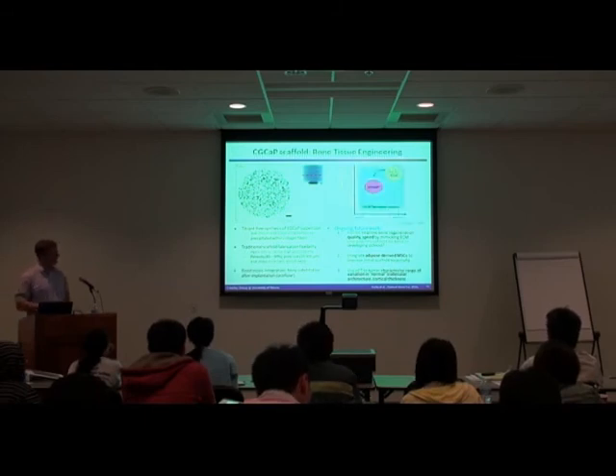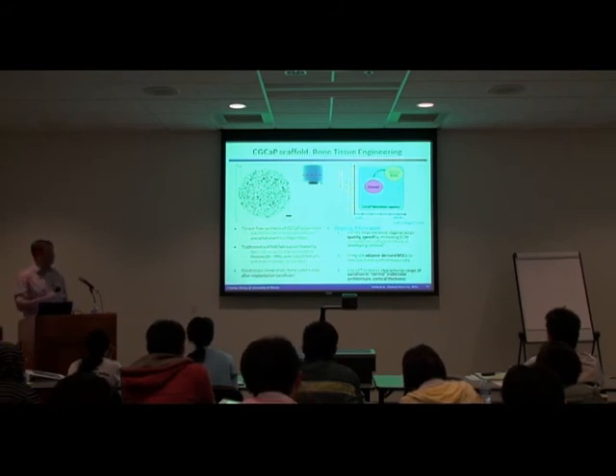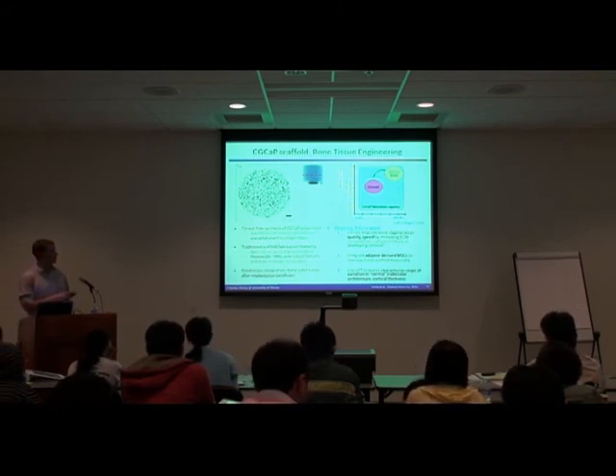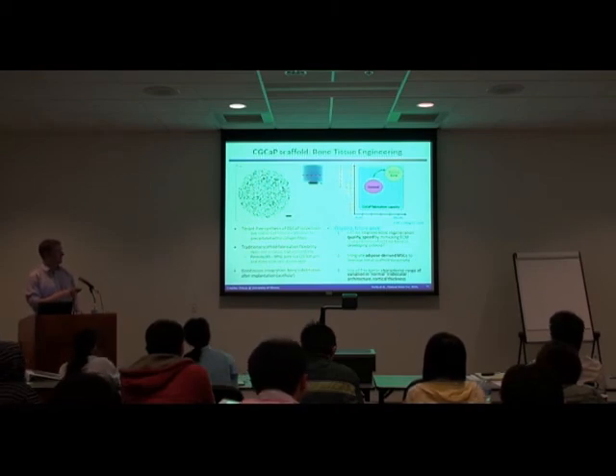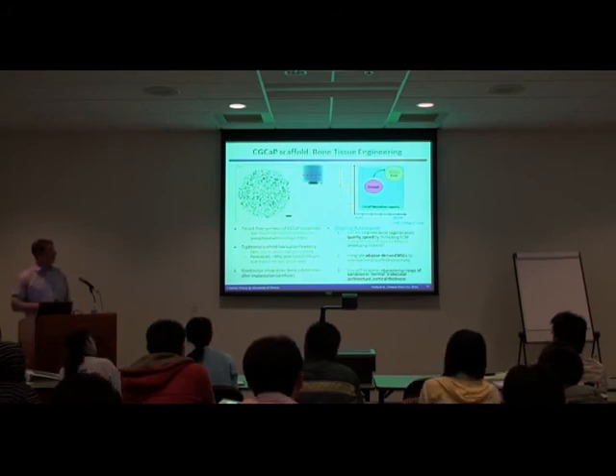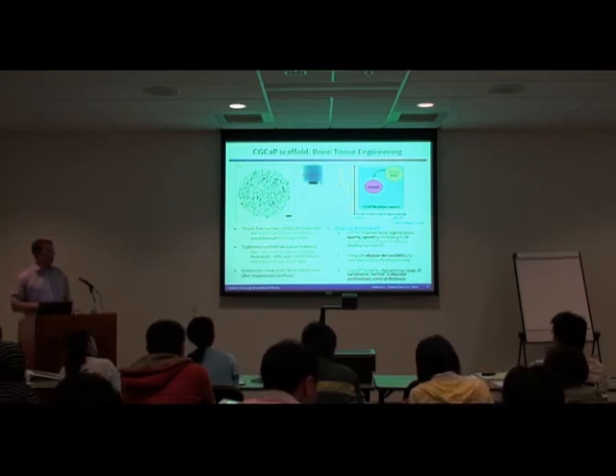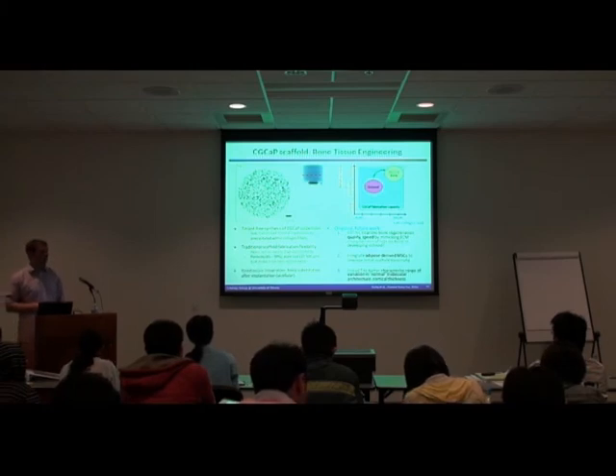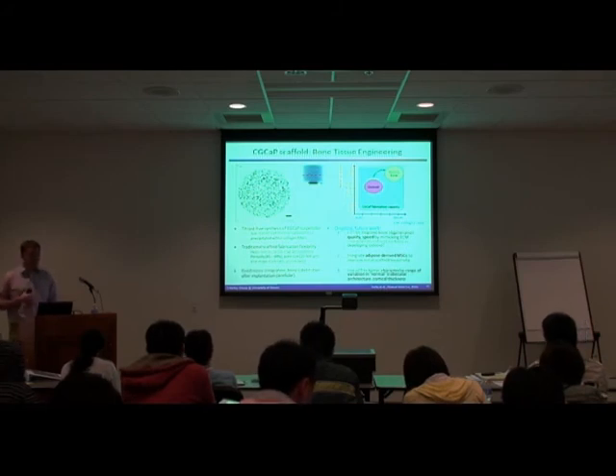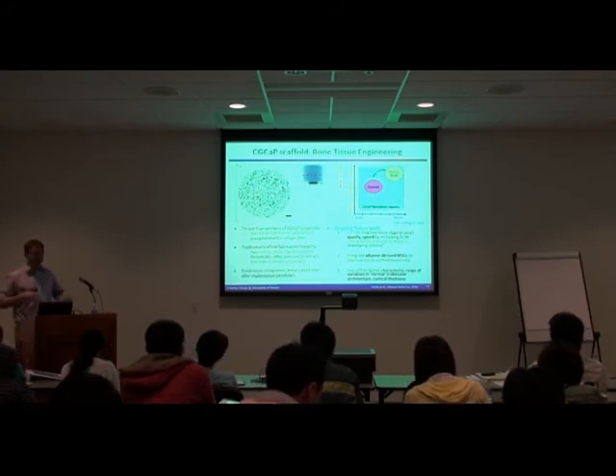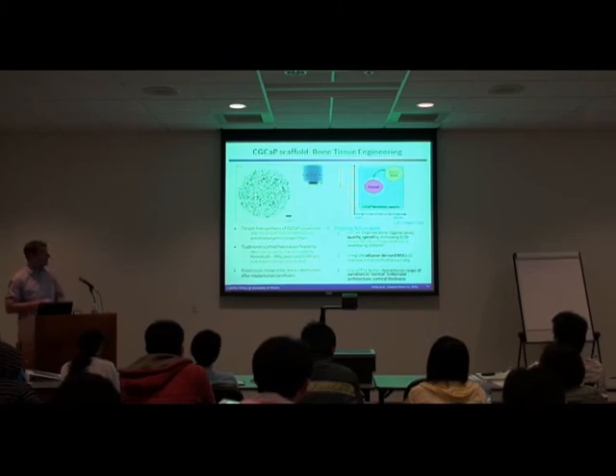The reason for that is that, going back to a developmental standpoint, if you look at how bone comes to be, you have an ossification event that takes place, and you have changes in the amount of mineral and the phase of mineral. And so what we've been able to do is make biomaterials so we can have the scaffold represent mineral stages at different points of the development process, to try to get an understanding of whether there is a more appropriate mineral phase and mineral content that allows rapid cell integration and rapid remodeling, as opposed to just putting in a material that mimics bone material, which never can produce huge amounts of bone. So that's one of the fun things we've been messing with.